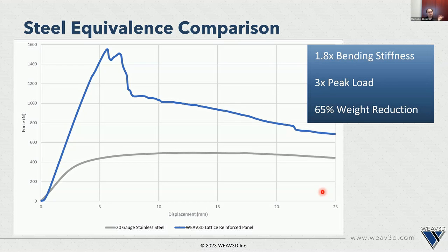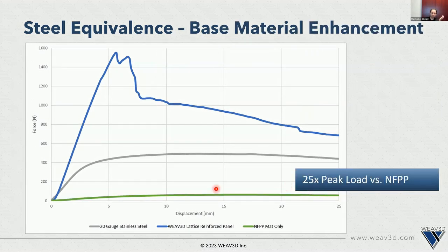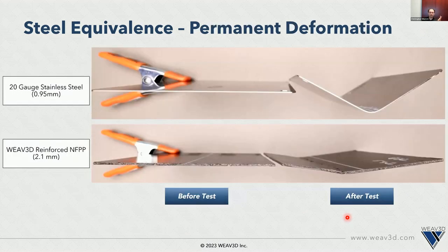And just to compare that against the natural fiber on its own, just to show you that the lattice is doing all the work here, that's the force displacement curve for the natural fiber mat by itself. So our solution is a 25 times improvement over that natural fiber mat. But the other important thing that I think a lot of people don't realize with thermoplastic composites is the amount of recovery capacity. So all of these samples that you see here were loaded to that 25 millimeters total displacement. If you look at these panels after what happened, that steel panel is permanently deformed.